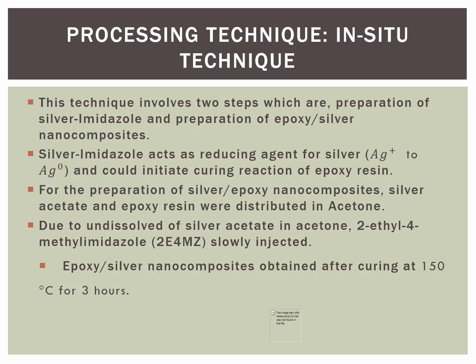Next is the preparation of silver epoxy nanocomposites. The silver acetate and epoxy resin with the fraction ratio were distributed in acetone. Since silver acetate does not dissolve in acetone and is only in suspension, an acetone solution of 2E4MZ was slowly injected into the above suspended mixture to dissolve the suspension, and after being stirred for 30 minutes, the solvent was evaporated under reduced pressure at 40 degrees Celsius, and at this point the formulation was free of solvent. Finally, epoxy silver nanocomposites were obtained after curing at 150 degrees Celsius for 3 hours.